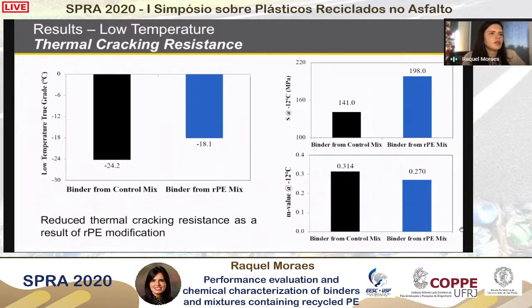And in terms of the thermal cracking resistance, we see a reduced thermal cracking resistance as a result of the incorporation of the recycled polyethylene. We can see an increase in stiffness and a decrease in the relaxation properties evaluated in terms of the m-value.